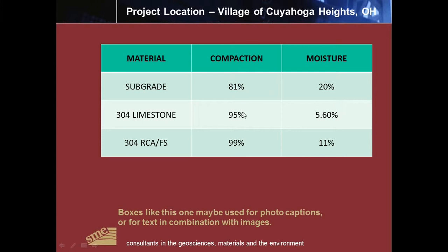On the limestone section, we obtained 95% compaction, and on the recycled concrete aggregate, 99% compaction. The additional rolling on the limestone did not improve the density any greater, so we reached a maximum density with the size of equipment that they had on site.